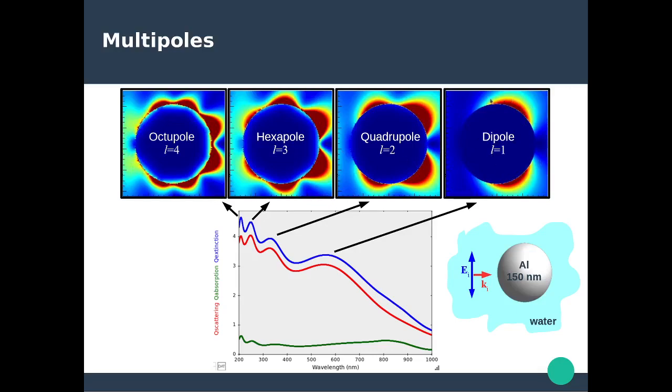You see that the dipole is not perfectly at the top or at the bottom; it's slightly offset to the right, and this is because of retardation effects. So as light propagates from left to right on this schematic, it takes time for light to propagate from one end to another, and by the time the optical wave arrives on the right hand side, the left hand side is already starting to decay and is less pronounced. So that's why you have this symmetry breaking left right.